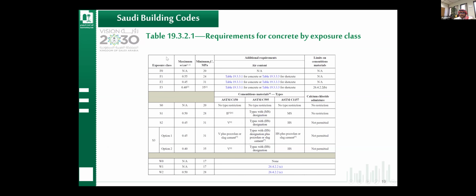Also, as you can see, these are the exposure classes. We have the maximum water to cementitious material ratio. We have here limitation on minimum compressive strength of concrete, and also we have restriction on cementitious material. So what type of cement we are allowed to use, and if we are going to use supplementary cementitious material, what other material we are including. There are some restrictions if you are in certain exposure classes with the calcium chloride admixture. So if you happen to use admixture, you sometimes have to watch out for the effect of these admixtures.